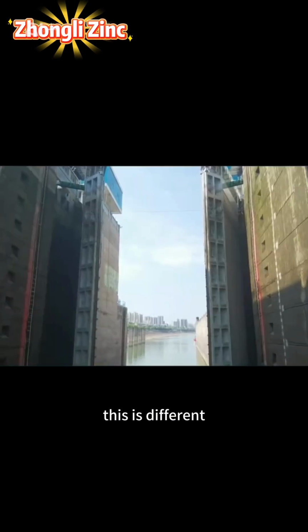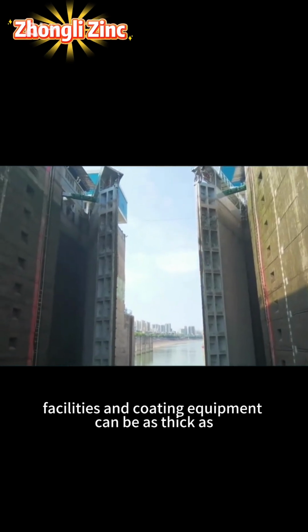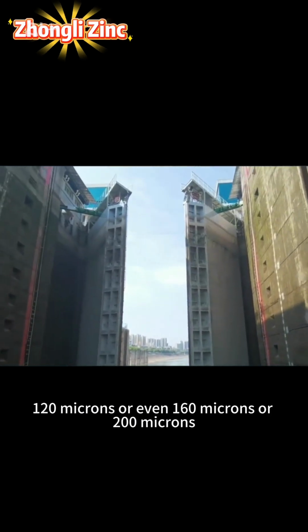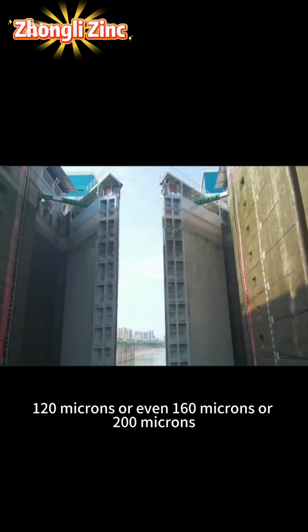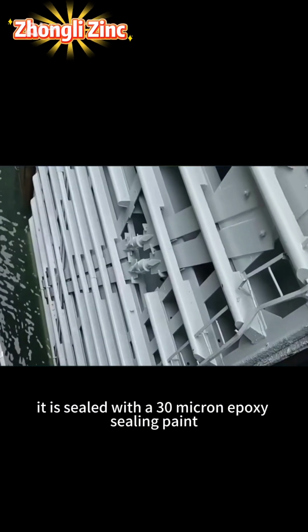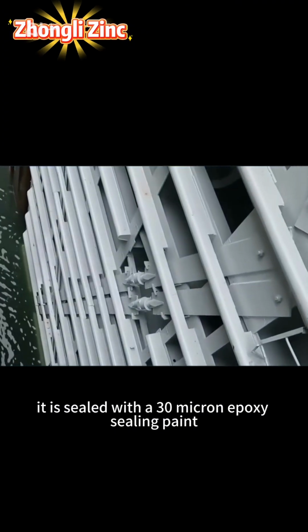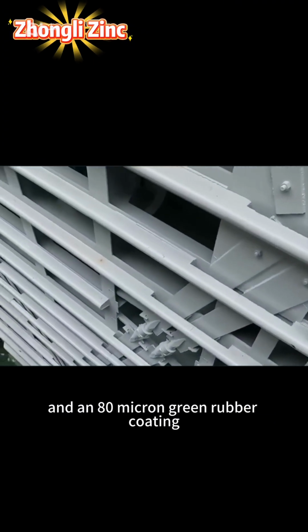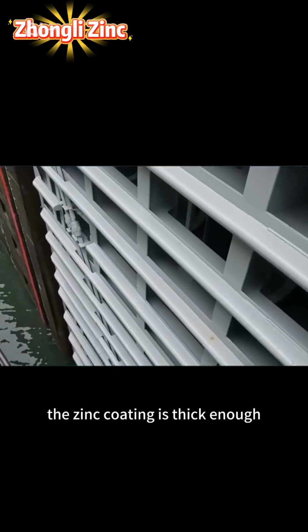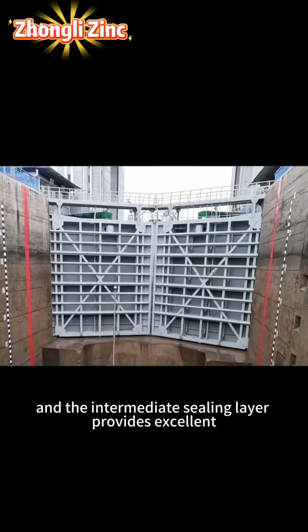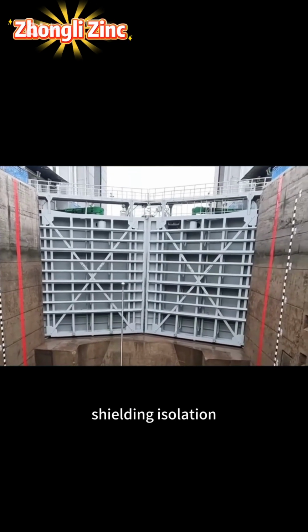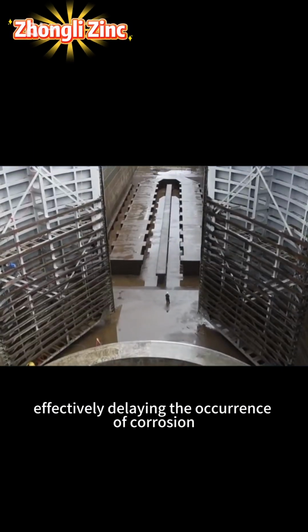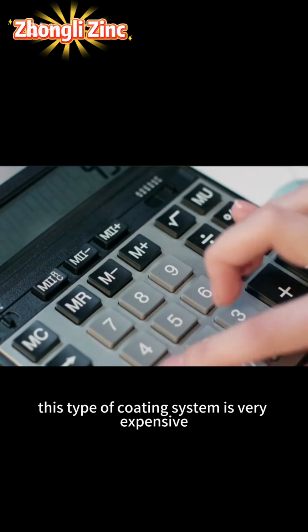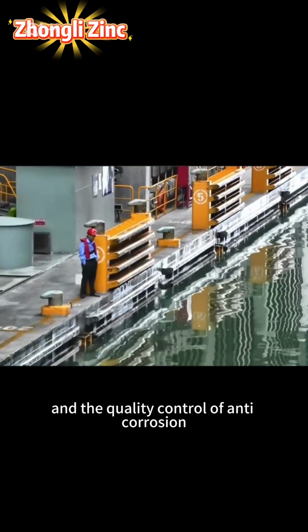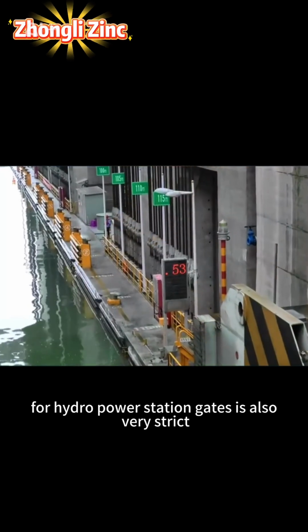This is different. The zinc coating on factory water conservancy facilities and coating equipment can be as thick as 120 microns, or even 160 microns or 200 microns. It is sealed with a 30 micron epoxy sealing paint, an 80 micron intermediate coating, and an 80 micron green rubber coating. The zinc coating is thick enough, and the intermediate sealing layer provides excellent shielding isolation, effectively delaying the occurrence of corrosion. This type of coating system is very expensive, and the quality control of anti-corrosion for hydropower station gates is also very strict.